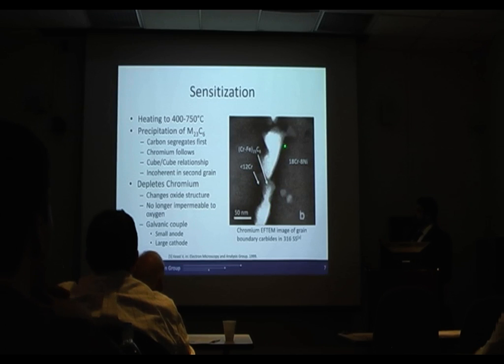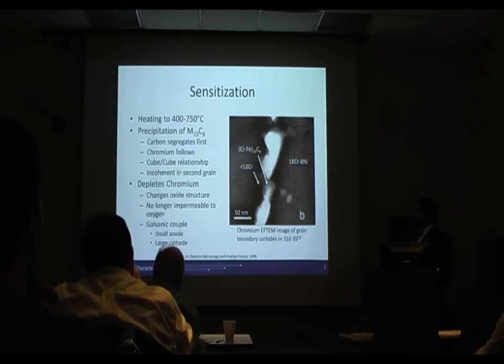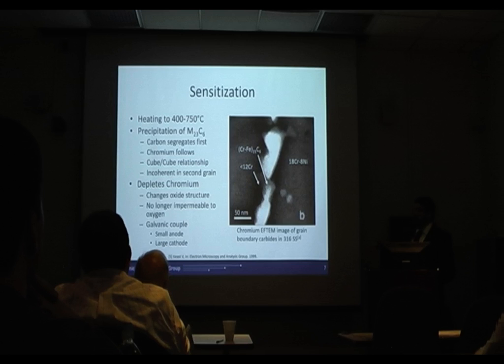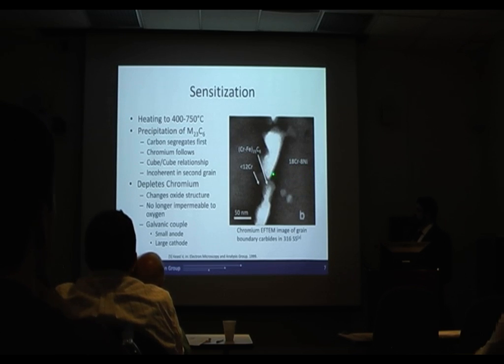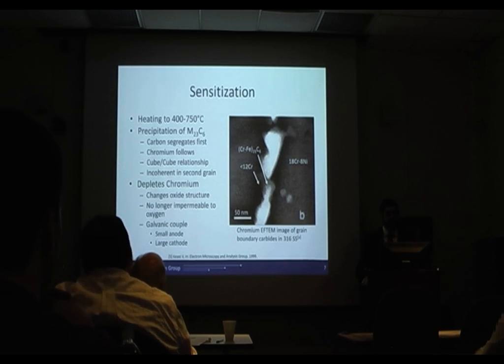So here in the center, you have the M23C6 carbides, where M is either iron or chromium, but primarily chromium, as you can see here. And then you have this kind of neutral gray for your matrix, and then you can see it's darker immediately around those carbides, which is because the chromium there is depleted. It's been sucked into the carbide. The problem with this is that it can drop it below 12%, so you change the oxide structure back to the normal iron oxide structure, and it's no longer permeable to oxygen, or impermeable to oxygen.